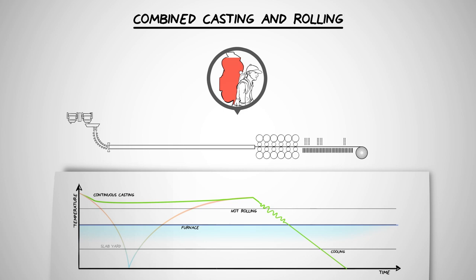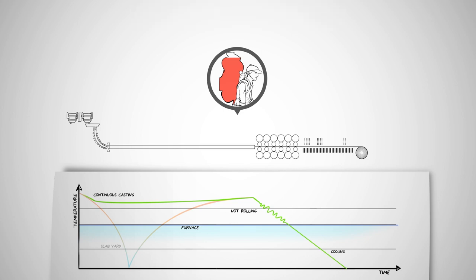Therefore, it's time to speed things up and get rid of the hurdles. Firstly, we will chuck out the tunnel furnace, which creates a lot of surface scale. This is replaced with a short induction heater, which additionally contributes to reduced energy consumption. Then we split rolling into two steps in order that the first rolling step can use the energy from the hot cast strand. Finally, cutting no longer takes place after casting, but at the end of rolling, just before the downcoilers.